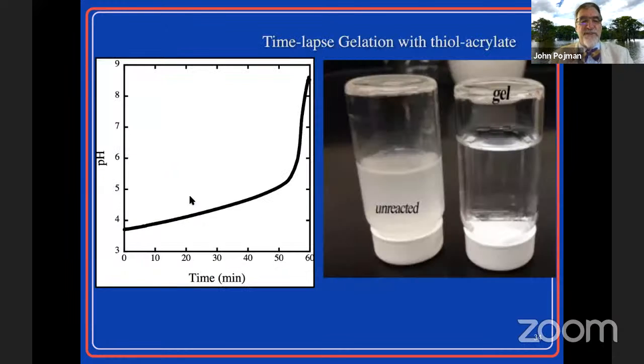This is just showing the pH as a function of time. And this is now the initial solution. And then after the pH goes up, it's now a gel. And you can see it's a clear gel.